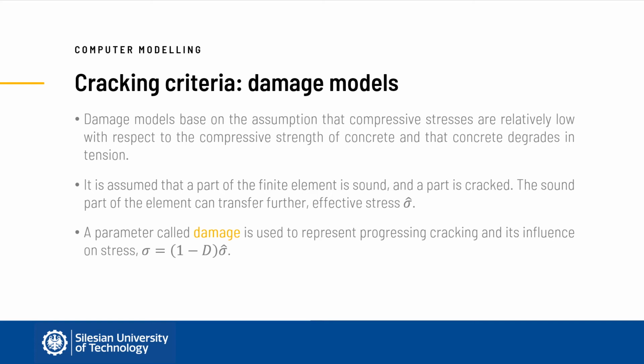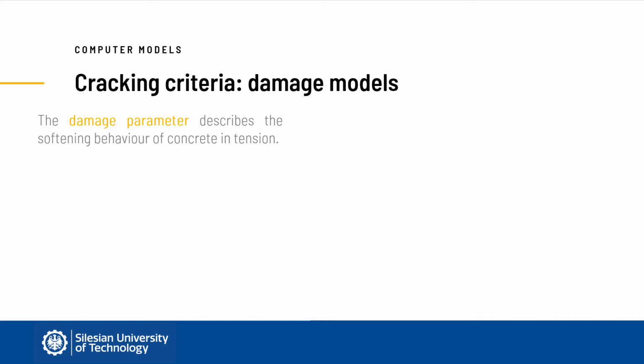The level of stress which can be still transferred by the element in which cracking was identified is defined by the parameter called damage. For an uncracked element, the damage is zero and the element can take full stress. With progressing damage to the element associated with progressing cracking, the value of the damage parameter increases and the efficiency to transfer stresses by the element decreases. This means that the damage parameter describes the softening behavior in tension.